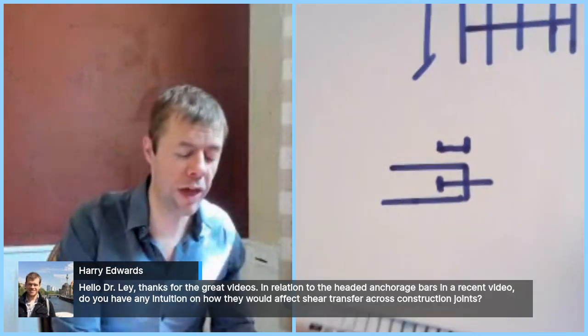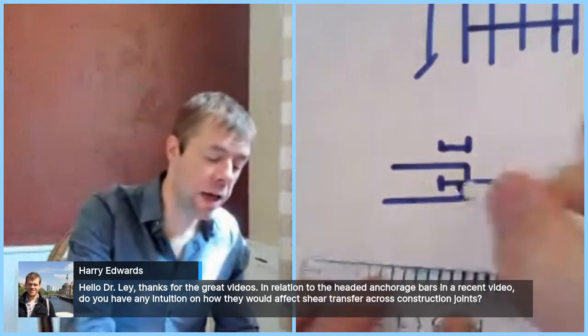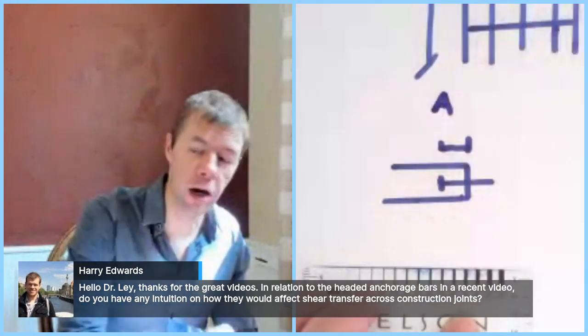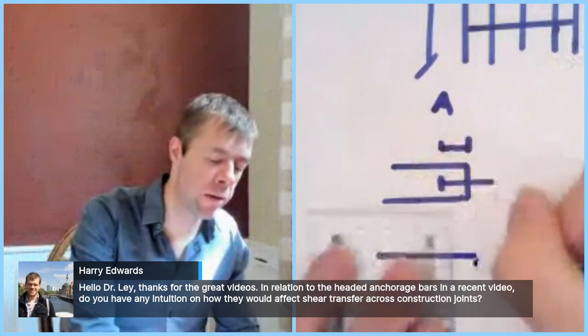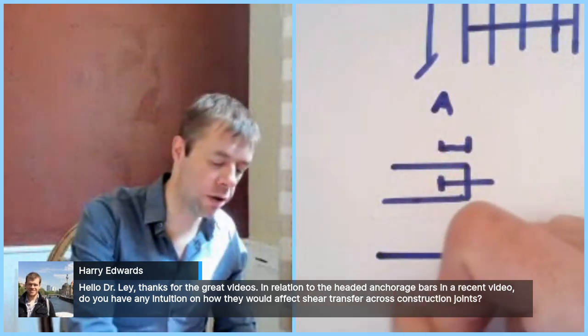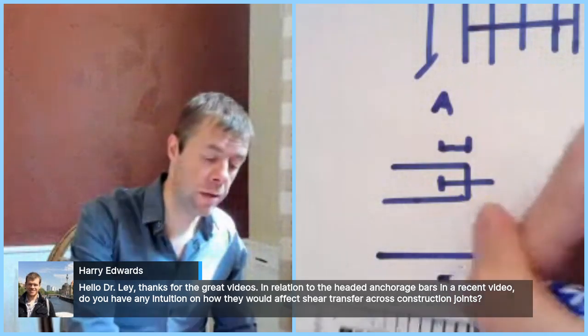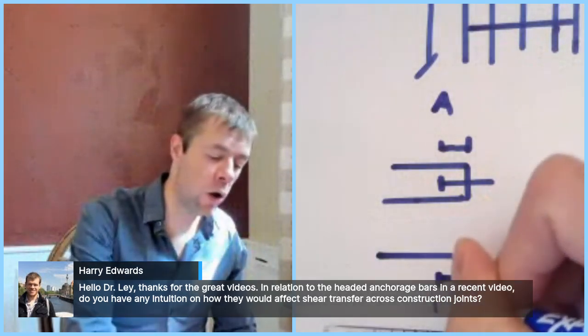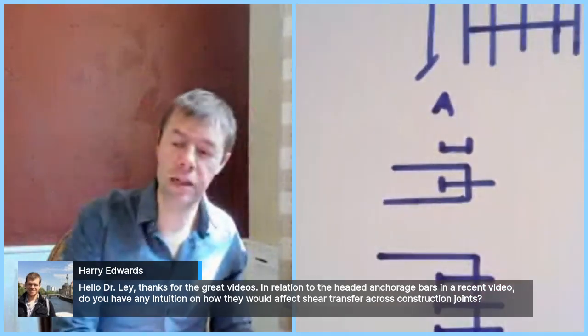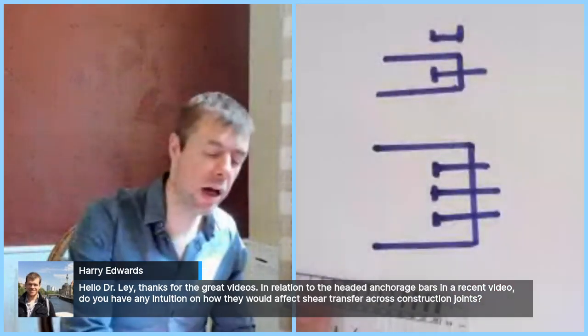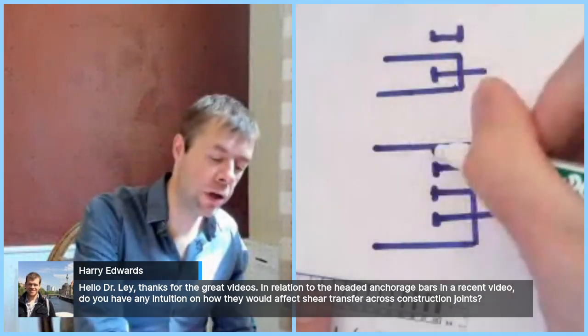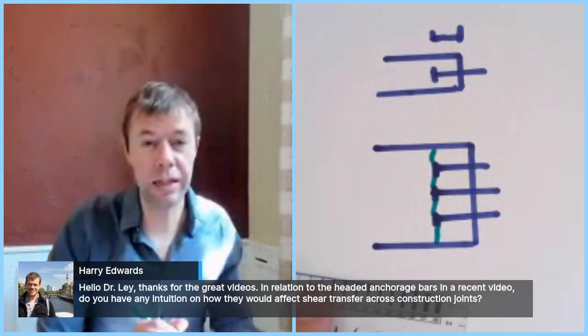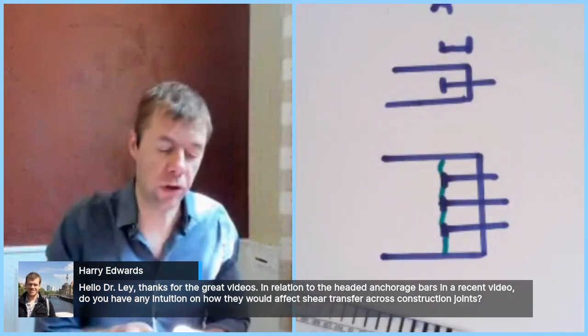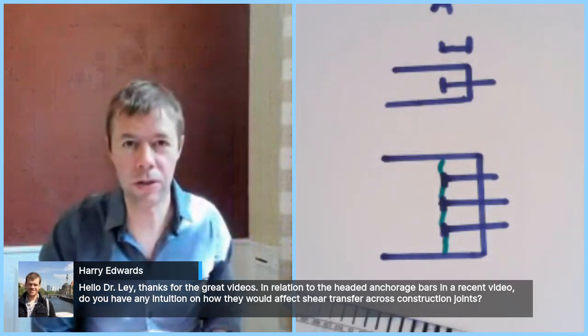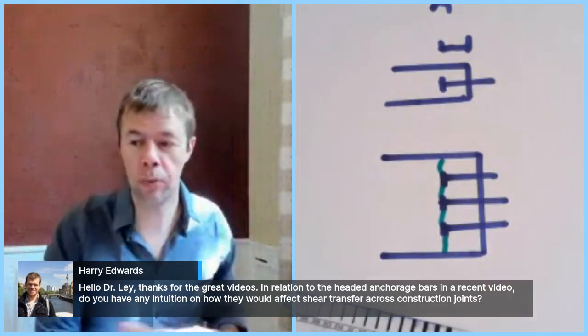Now, one thing to watch out for with headed bars that people actually don't talk about a lot is that if my eye is above looking down and I have a whole series of headed bars in a row, people don't talk about this, but it's real. I've seen it in testing. A whole series of headed bars in a row. What can happen is these heads can create a weak plane inside the concrete, and you can get a crack form right along here. I've seen it. It's happened. And I don't know if they're going to address it eventually or not. Headed bars are pretty recent in the code, but I think eventually at some point they will if they become more popular.